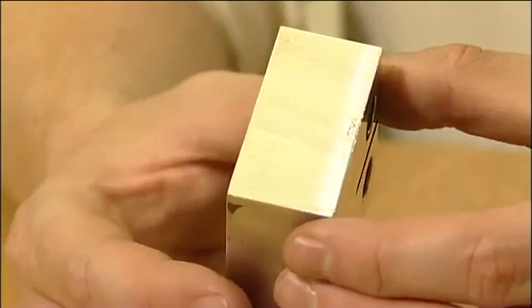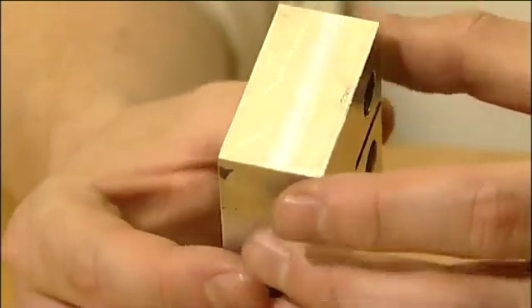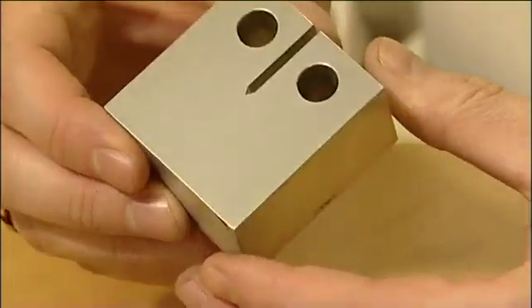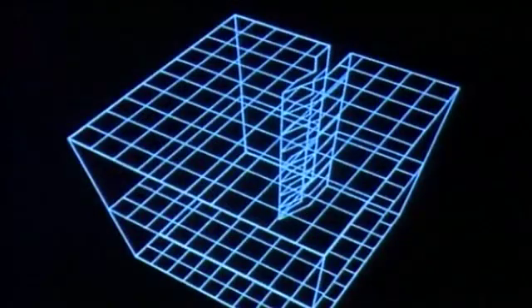If the material were very ductile, then you would not see such a flat fracture, and it may not be possible with a sample of this thickness to obtain a plane strain fracture toughness result. In that case, you would either have to use a thicker sample or to use a measurement such as CTOD instead. Have a look at what happens within a test specimen when a crack is loaded.